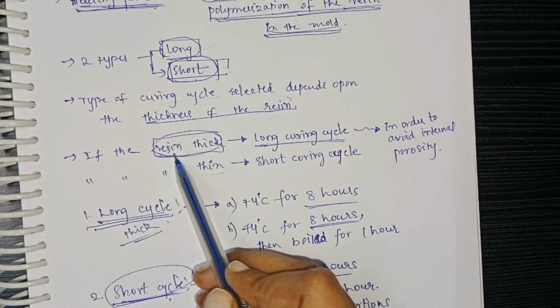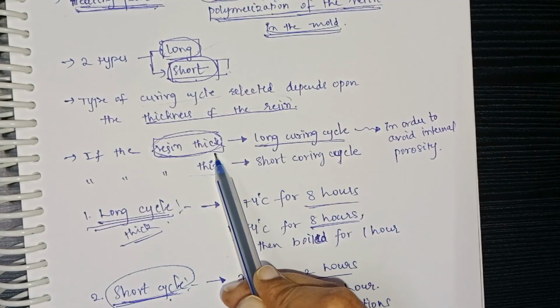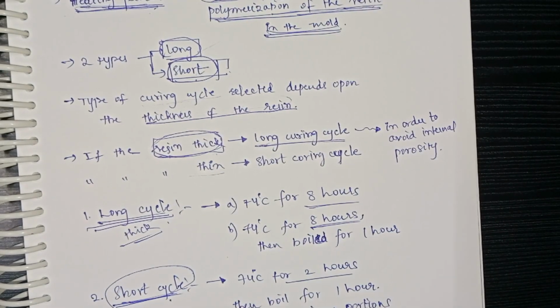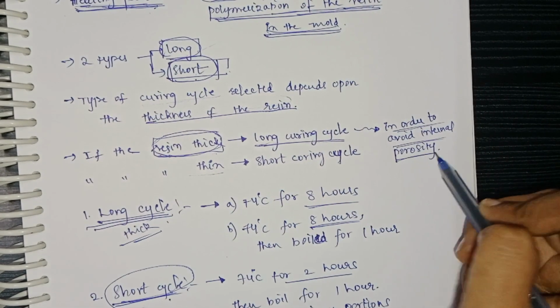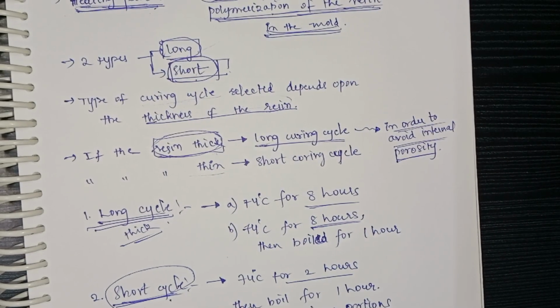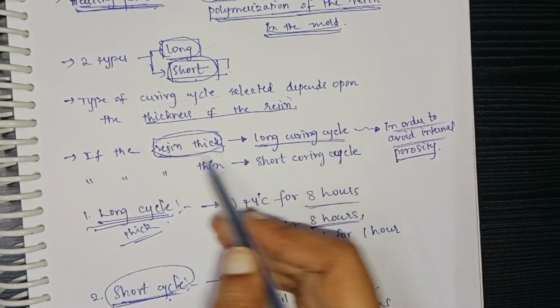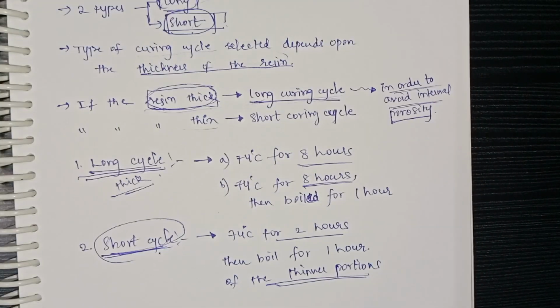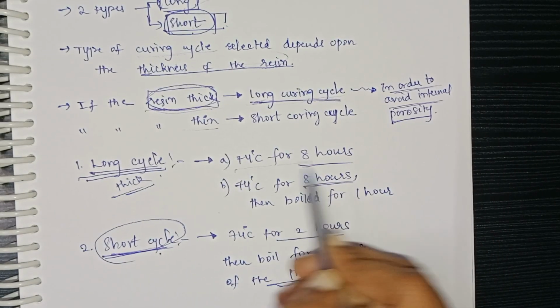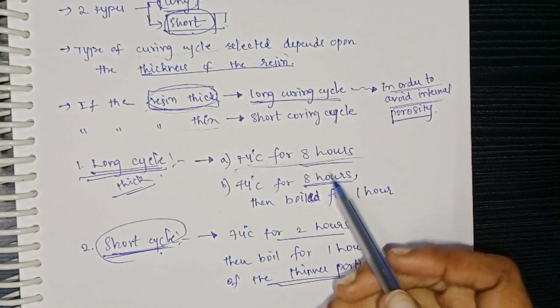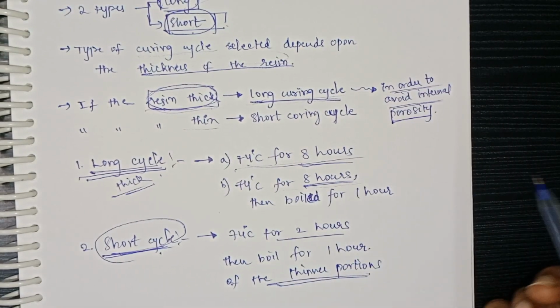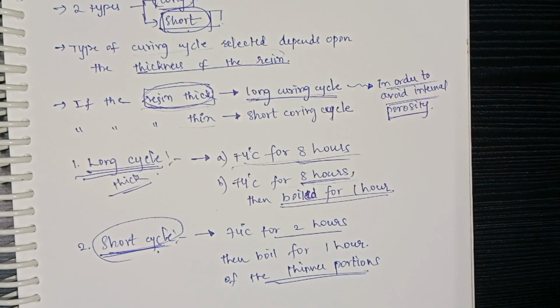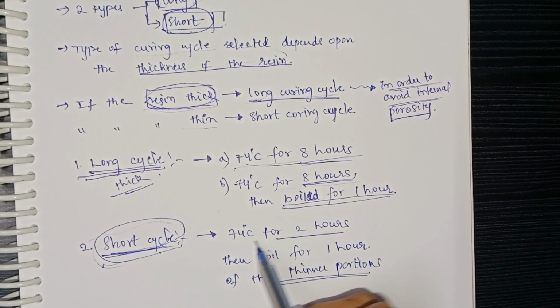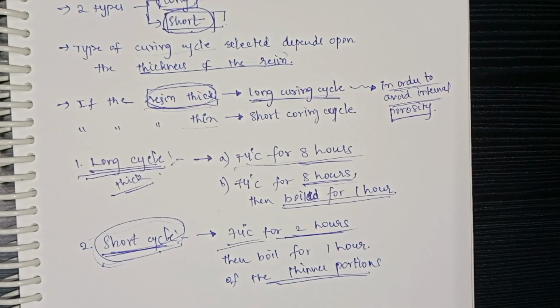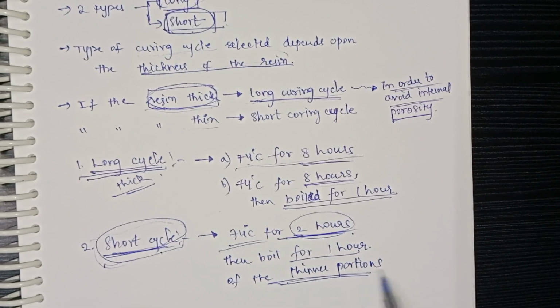Long curing cycle is recommended for the resin which is thick, because we are going to avoid internal porosity. In order to avoid the internal porosity, long curing cycles are recommended for thicker resins. This long cycle is done at temperature 74 degrees for 8 hours, then boil for 1 hour. Whereas in short curing cycle, at same temperature 74 degrees, but for short duration, that is only for 2 hours. Then again boiling it for 1 hour of the thinner portions.